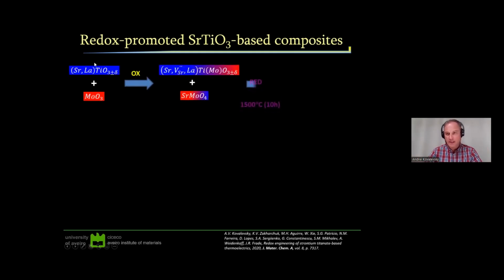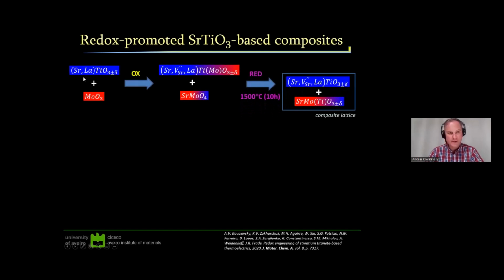The matrix, strontium titanate-based material substituted with lanthanum itself, is a good thermoelectric. Addition of molybdenum as a redox-sensitive additive: first we process under oxidizing conditions, forming a mixture where molybdenum cations are basically already distributed between scheelite and perovskite phase, then eventually applying reducing conditions which result in the formation